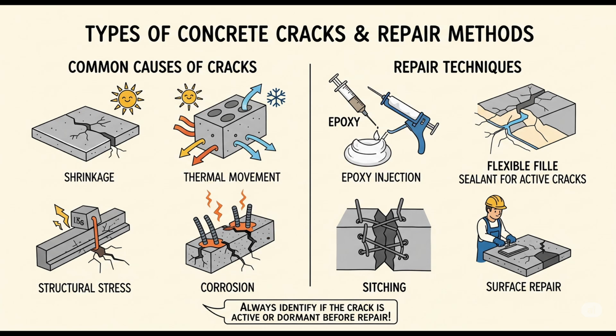Then I imagine moisture and certain chemicals would speed that up significantly, like near the coast. Precisely. The presence of chlorides, for instance, which is common in coastal areas with salt-saturated air and humidity, greatly accelerates this corrosion process. The implication is severe. Corrosion significantly reduces the effective cross-sectional area of the rebar, compromising the structural integrity. It's particularly critical in pre-stressed concrete, where the steel is already under high tension. Any reduction in its cross-section is extremely dangerous there.